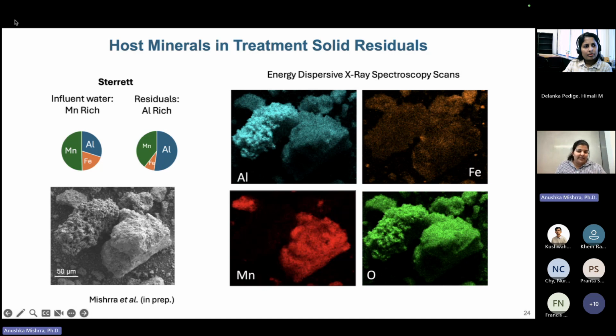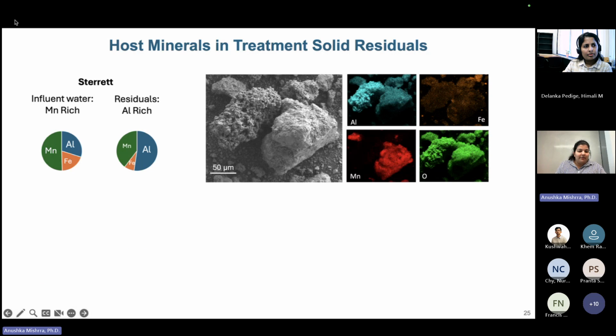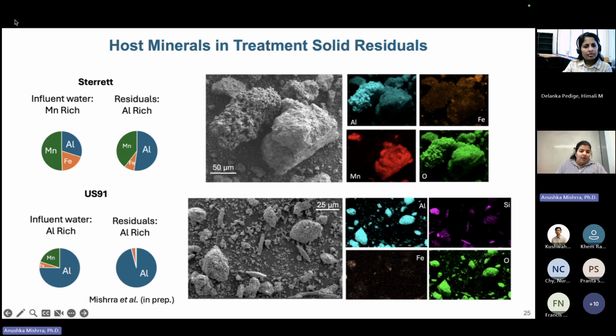Now, we sampled so many sites, so it's worth comparing some of them. So here I will draw a comparison between Sterret and US91. What is interesting between the two is that when you look at the residues, both are aluminum rich, but the influent was different in the enrichment. Sterret had more manganese enrichment, whereas US91 had more aluminum enrichment. So the fact that the residuals ultimately have aluminum, it's worth comparing to see what the differences are. One of the key differences is that even though more manganese was present in the fluid for US91, we didn't see any manganese in the treatment solids. And in fact, we saw mostly aluminum and silicate present in the treatment solids, like you see here.